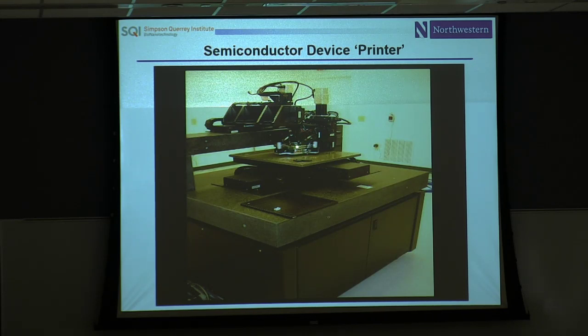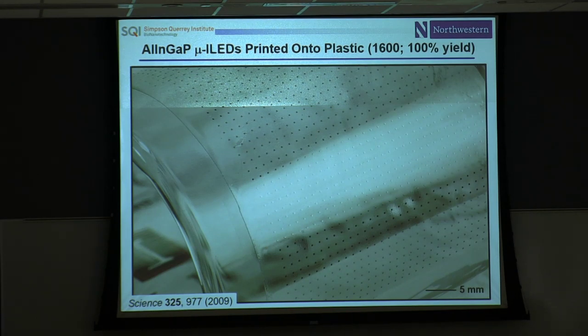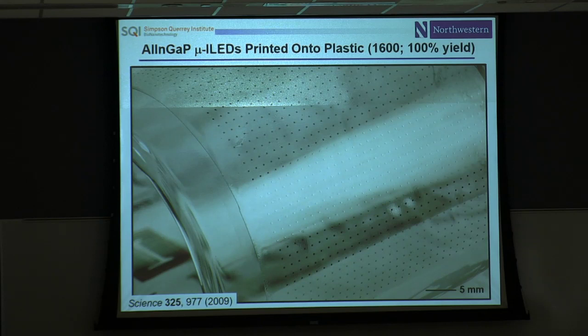You can bring together mechanics, materials, and manufacturing to construct very high-performance flexible electronics. This is an example: 1,600 tiny micro-scale AlInGaP LEDs, 100% yields, about 200 microns on a side and 200 nanometers in thickness, printed onto a sheet of PET and subsequently wrapped around a cylindrical support. AlInGaP is a very brittle material, yet in these very thin, small forms they can be bent to that kind of radius of curvature and don't pop off the surface because of that linear downscaling of energy release rate with thickness.